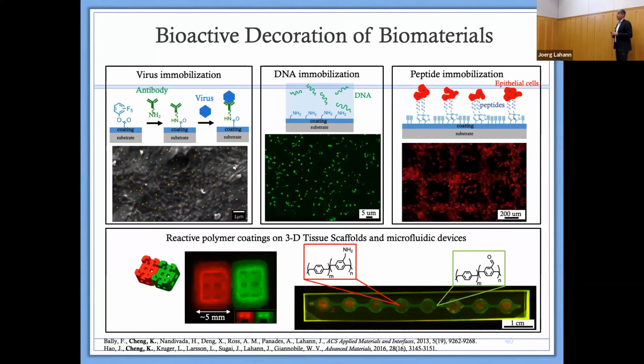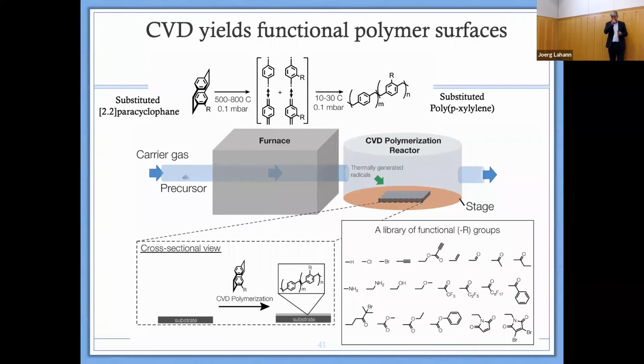And the point is really to develop processes that give you access to very well-defined surfaces. And then obviously you want to have very little side effects. If you look at some of the early stent coatings that were out there and some of the issues with that, often it was actually the solvent that people used to deposit the polymer that gave you the toxic effects. So often it's the small initiators, plasticizers, solvents that people use to deposit this material that actually make it toxic. In our case, we avoid all of this by depositing our polymers from the vapor phase.